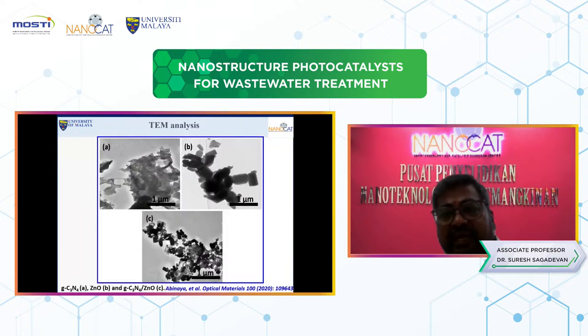And you look here, again we confirm the morphology of this composite. A represents only graphitic carbon nitride. It has a sheet-like morphology, which is clearly seen from the plain image of A. B is the structure of zinc oxide. But C is the composite. In the composite images, you can clearly see how the zinc oxide is incorporated and wrapped with the graphene sheet. That is evidence for the successful formation of this composite.